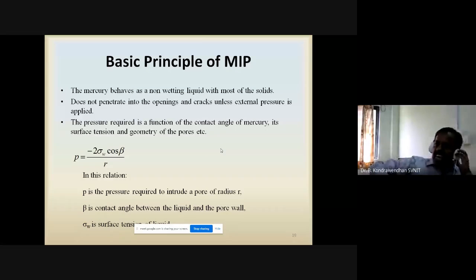As I mentioned earlier, mercury intrusion porosimetry is based on the Washburn equation. So what is the Washburn equation? Mercury behaves as a non-wetting liquid because its contact angle is more than 90 degrees. It has 135 degrees. That's why it is a non-wetting liquid, and it does not penetrate into openings and cracks. I have shown this in an earlier slide also. Even though mercury is spilled on a plank which has a number of cracks, it does not go inside the openings or cracks unless you apply some external pressure or force.